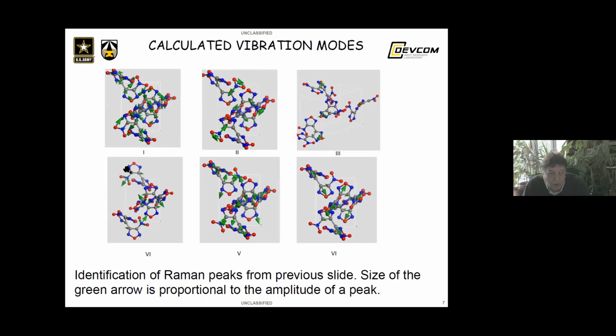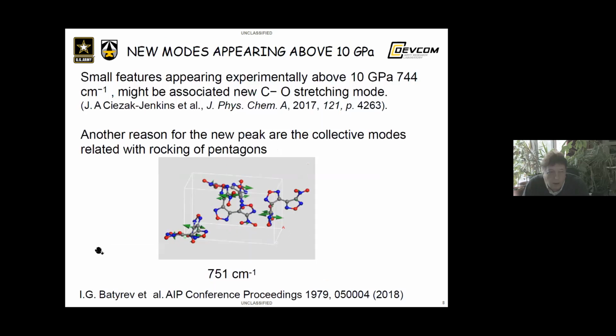At 30 GPa, we are far from pressure-induced decomposition. But there are new peaks emerging above 10 GPa. There are several peaks around 744 inverse centimeters. This mode might be associated with a new C-O stretching mode. The decomposition mechanism based on the new molecular mode proposed for LLM-172 is that of isomerization of one of the peripheral nitro groups into CONO arrangements and subsequent NO loss.